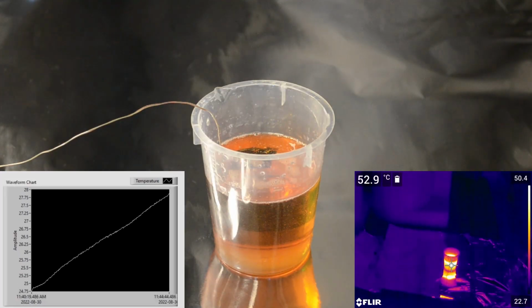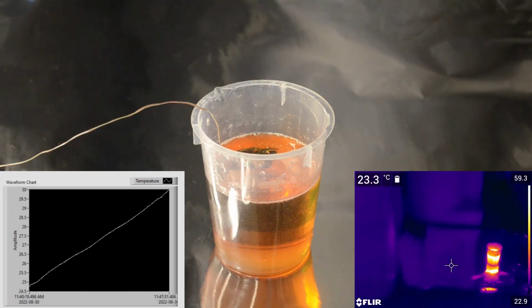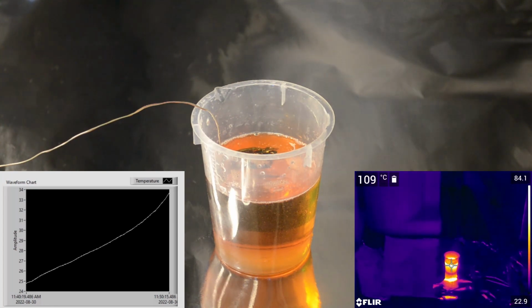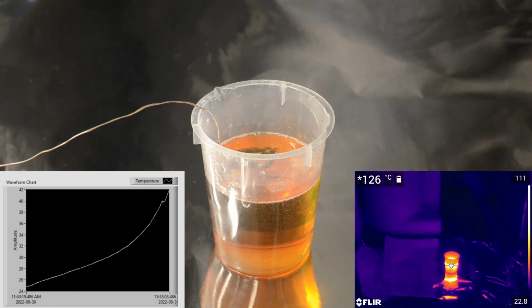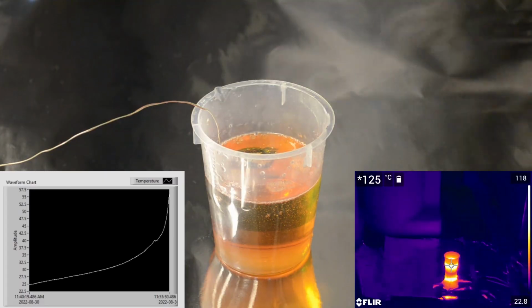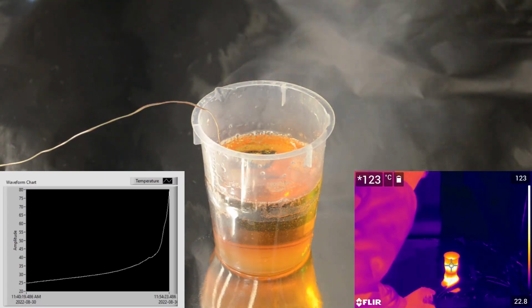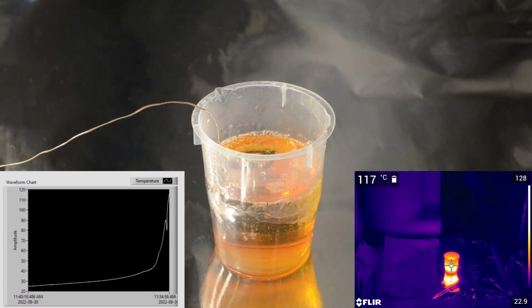As a result, large volumes of resin mixed in one container can heat up to dangerous temperatures quite quickly. Here, we have mixed 150 grams of resin with a gel time of 20 minutes in a cup. It can be seen that the resin starts to heat up and begins to produce vapors and melt the cup.